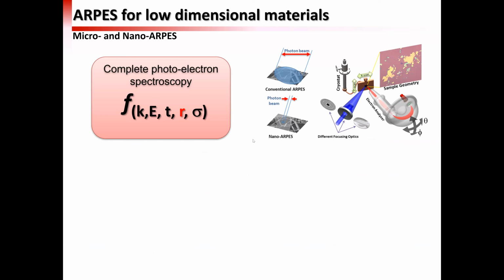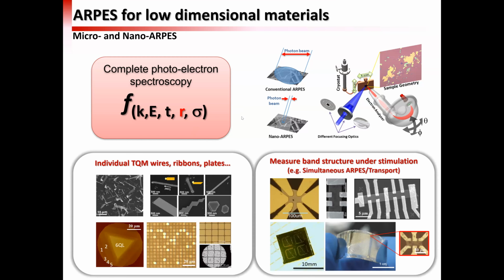tantalum triselenide. So when we study low-dimensional materials using the ARPES method, in addition to regular ARPES, we sometimes use micro and nano ARPES measurements. I think Professor Kondo showed such measurements yesterday. By doing micro and nano ARPES, we can focus the beam spot to a very small area, and therefore can study small structures, for example nanowires, ribbons, and plates.